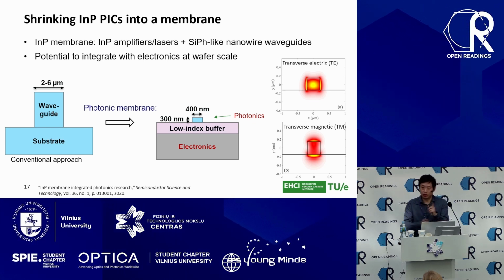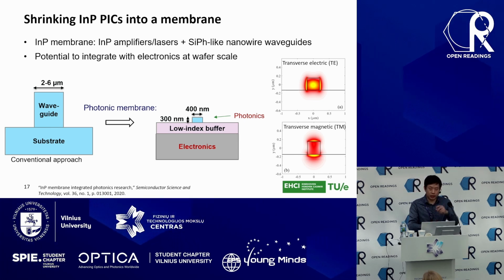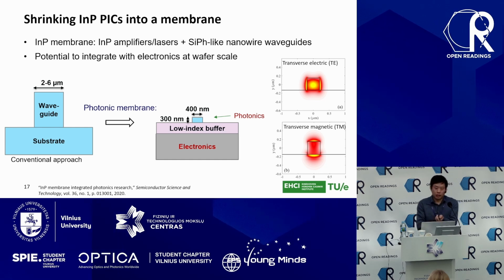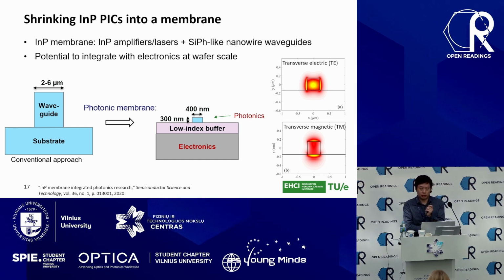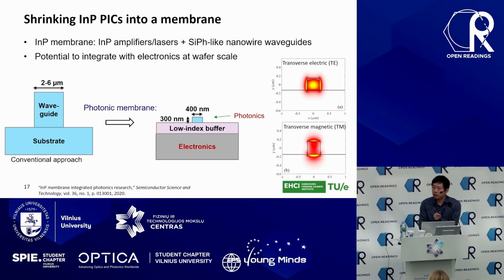in a very large laser diode, typically 2 to 6 micrometers in width. And what we're trying to do is to shrink the entire diode structure into a much smaller cross-section. As you can see in the middle, we try to separate the indium phosphide waveguide apart from the substrate, so that it can have a much higher index contrast, leading to sub-micrometer dimensions. So in terms of waveguide, it's very similar to silicon photonics, but it's made of indium phosphide.